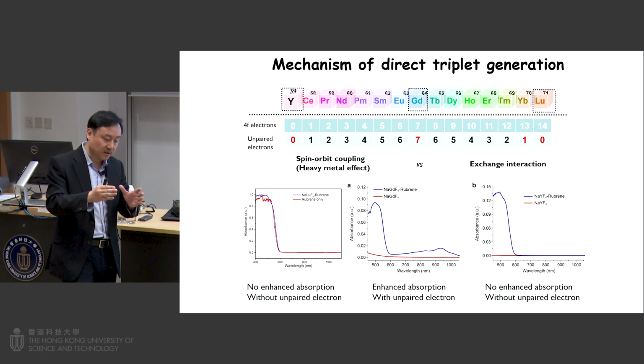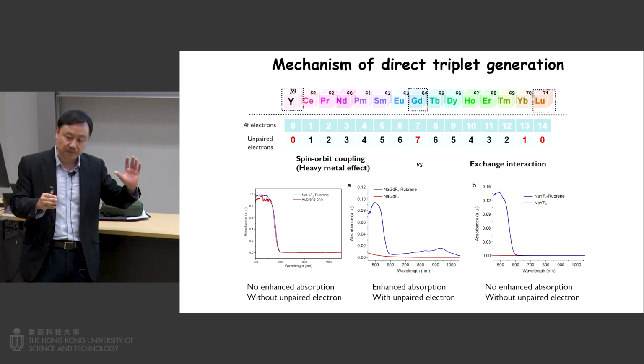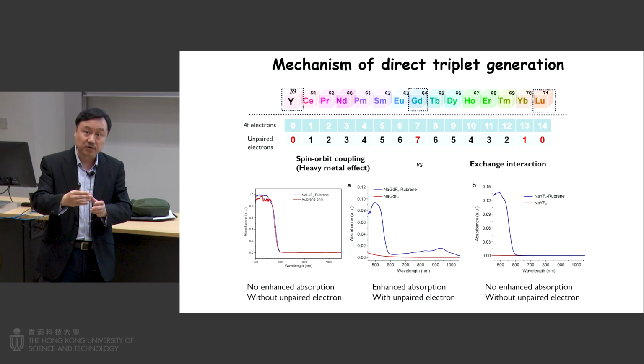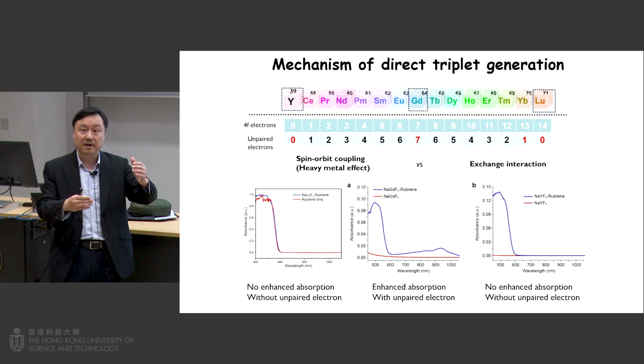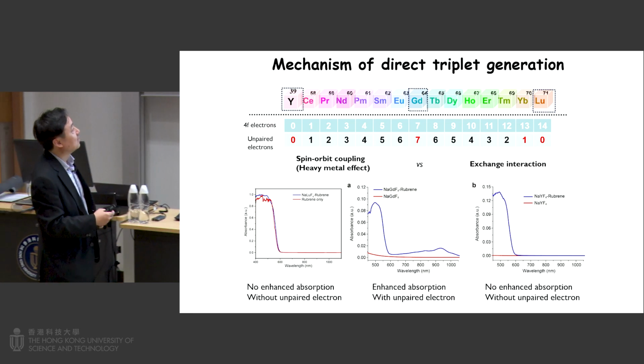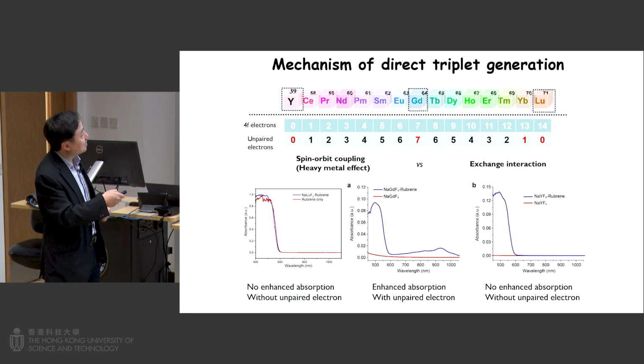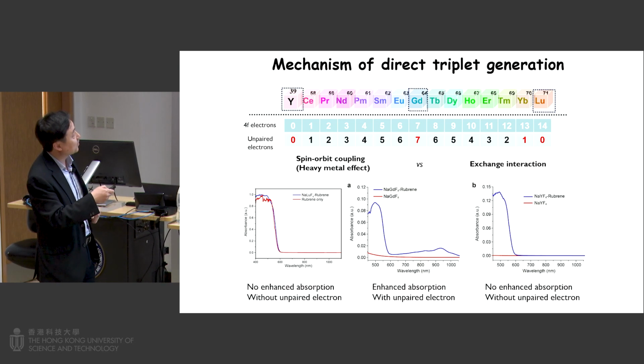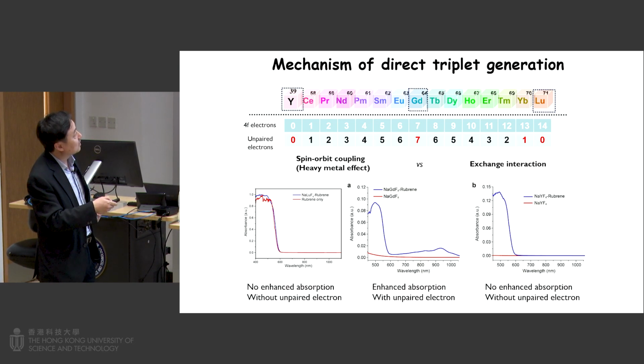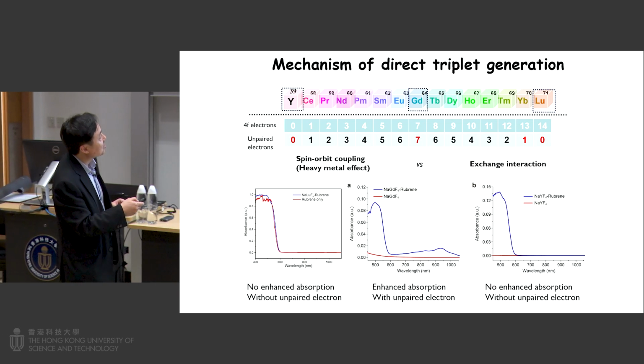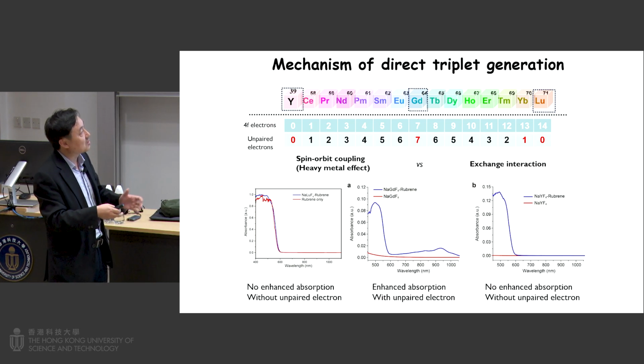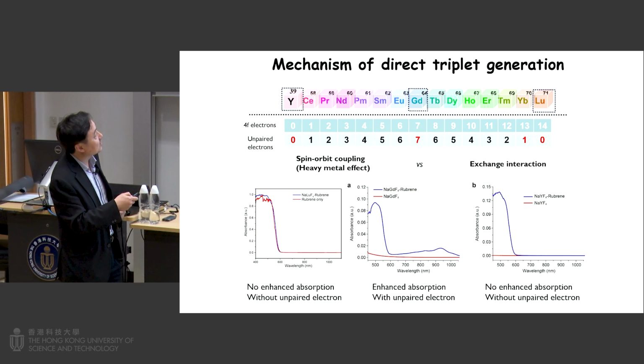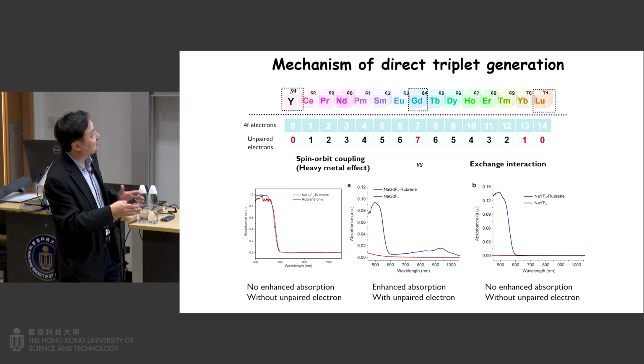Okay, it's not so conventional. There's also debate about this triplet generation. You can use heavy atoms, or you change the spin orbit couplings, the energy mappings, the splittings. From our experiment, we did a series of studies across the lanthanide series. It turns out that the number of unpaired electrons plays a significant role here. If you look at Gd, Lu is obviously a heavy atom, but it turns out Eu and Gd have more unpaired electrons.